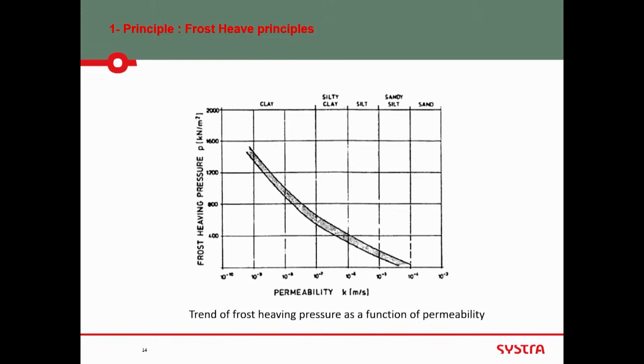So what is the experiment? The experiment is triaxial, where you allow the water to come into the sample, you freeze the sample, water is coming, but you restrain the sample from heaving. So you confine it, like with the oedometer test, and you apply a pressure so that the change in volume of the sample is 0. So this is the pressure which is developed. In this case, you see, for example, let's say silt, I'll take silt, 10 to the minus 6 meters per second, you get 400 kPa.